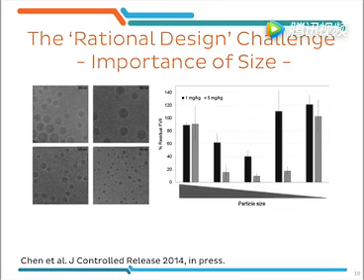versus, sorry, this is what we have on the y-axis, versus the particle size of the respective particle formulations. As you can see, it's not the very large or very small particles, but rather the particles of a specific intermediate size that are the most potent in knocking down this gene. So a specific nanoparticle size is needed to get the best in vivo effect.